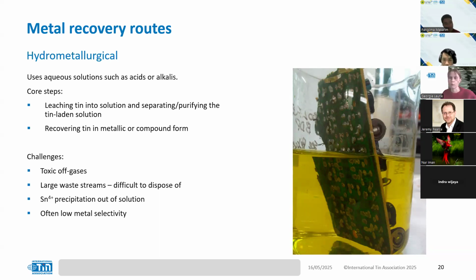For example, a recent study combined hydrochloric acid with sodium chloride to enrich the chloride content, which resulted in almost 95% tin leaching from the PCB material. But the one challenge really with acid leaching is reprecipitation, when tin 2+ is oxidized to insoluble tin 4+.